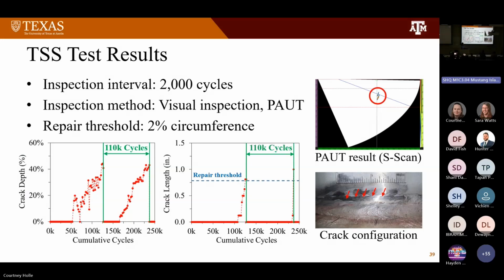During testing, we did an inspection every 2,000 cycles using visual inspection and PAUT. We used acetone for the visual inspection. While the pole is under cyclic loading, we put the acetone on, checking if it is seeping into or out of the crack openings. We also used PAUT, and a sample of the results is shown on the right side.